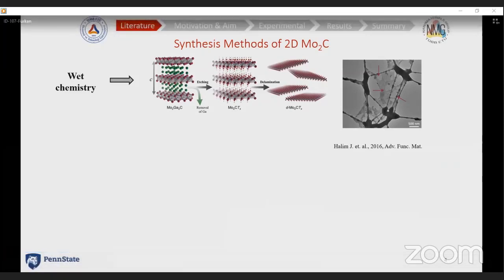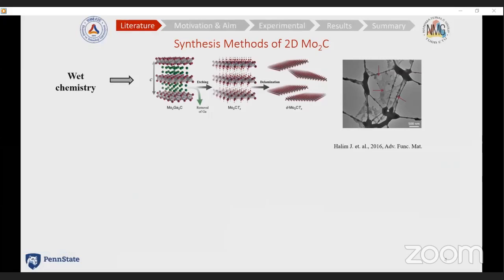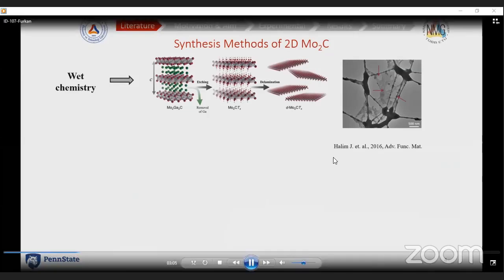And this is a top-down method, and so you have a starting precursor, which is called MAX phase. For molybdenum carbide, this is molybdenum gallium carbide. And in this method, since the bond between molybdenum and gallium is metallic, you can basically etch the gallium atoms, gallium layers, by an acid treatment, and then by a simple sonication or hand-shaking, you can delaminate the 2D flakes.